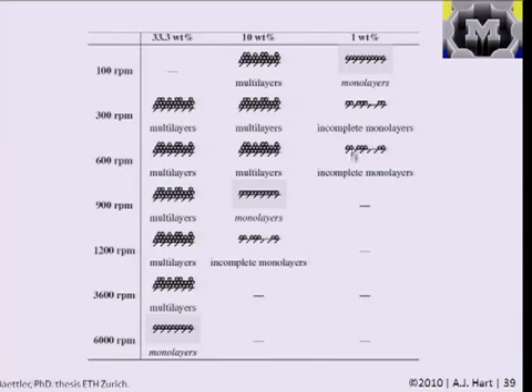monolayers, meaning there weren't enough particles, or the particles were taken away too fast, and these resemble large gaps between the domains. So when it's said that there's a monolayer here, it means that you have fairly tight two-dimensional packing of the particles, but there are these individual domains with defects, or analogous to dislocations. And when you have incomplete monolayers, it means you have a substrate with just groups of particles that are isolated from other groups of particles. And then if you have too many particles in the system, or you're not taking them away fast enough, then you end up with essentially heaps of structures.